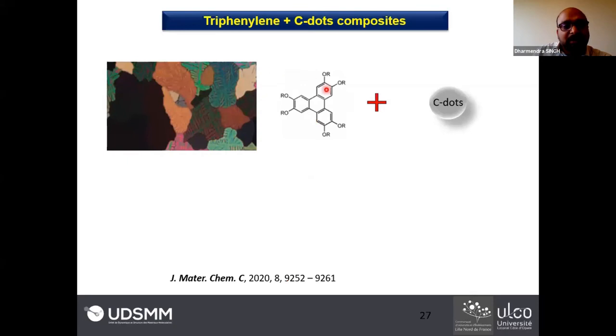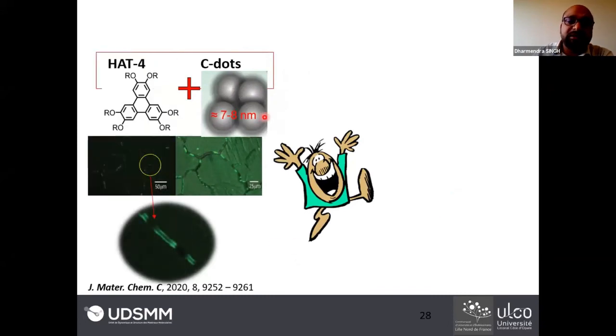Later on, we also took one triphenylene system, HAT4, and we dispersed some carbon nanodots in this system. Recently we published this in the Journal of Materials Chemistry C. As you know, these nanomaterials, especially carbon dots, have a self-assembling nature, and they can self-assemble inside any matrix and form a network. We found that these carbon dots create a network inside the HAT4 matrix.